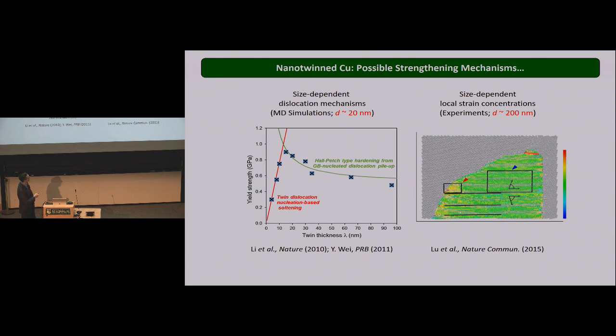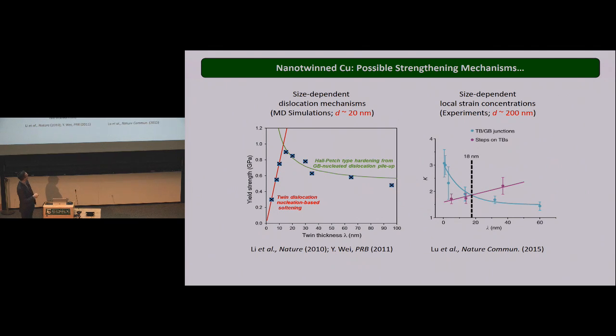experimentally, it was observed that, in fact, there are size effects in the stress concentration near the interfaces here. So this is an experimental work. And what they found is this stress concentration actually depends on the twin size. So that could possibly be another mechanism by which we see those size effects.